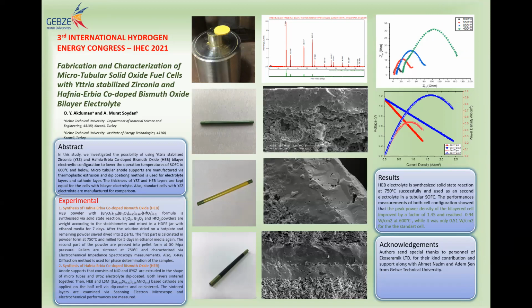In the study, we developed or synthesized an electrolyte material called Hafnia Erbia co-doped bismuth oxide, which is a high oxygen ion conductor. We used oxide versions of Erbia, bismuth oxide and Hafnia powders to synthesize the HEB powder, in short.